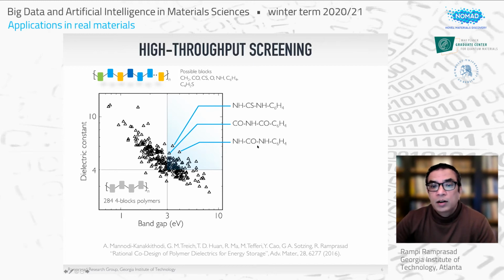The bottom one here is the urea, NHCO, NHC6H4. It's what you use to make fertilizers. We were proposing that we make a polymer out of this urea, polyurea. And in this case, the CO is replaced by CS, which is a thiourea. So basically, that's a polythiourea, and this is a polyimide.